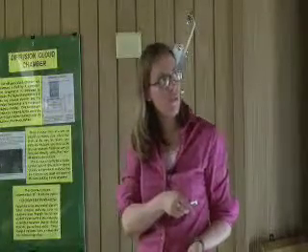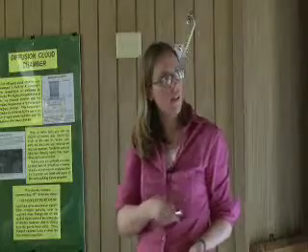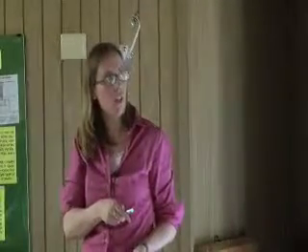So the magnetic field looks like this in time. And then we look at the sample by shining X-rays on it and collecting the electrons that come off of it. And these X-rays are pulsed, and that has about a 90 picosecond duration for the pulse. So 90 times 10 to the minus 12 seconds.